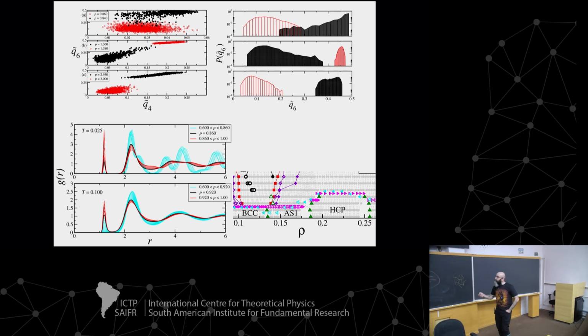If I analyze the g(r) now in this isotherm, you can see that the fluid phase to the left of this point, this blue system, is a little bit more ordered, and when I go to the other side, it is a little bit more disordered at long range. And more interesting, this one looks at short range a little bit more like the BCC, and the other one a little bit more like the amorphous phase.